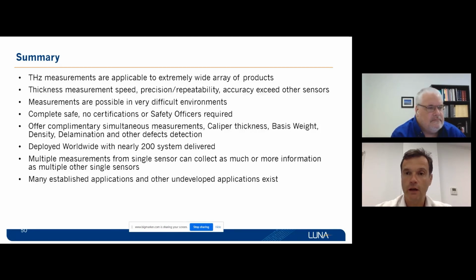Great, thanks for that. This next one here is from Leon Vegas. He would like to know if you can measure an aircraft's top coating on a composite material substrate with a copper mesh. Yes, and in fact, that's one of the applications that we have quite a few customers working on. So you can generally measure multiple layers at once. You might have a top coat, some intermediate coats, and then primers, etc. And then, of course, you hit whatever your conductive layer might be, a copper mesh or aluminum or carbon fiber, and that's the last layer you could measure.